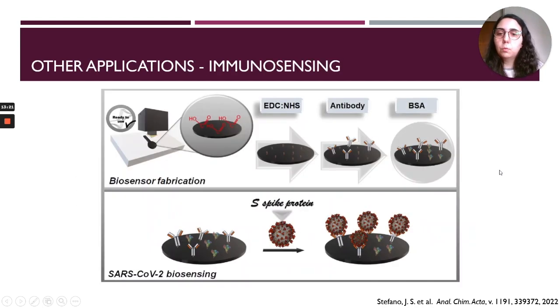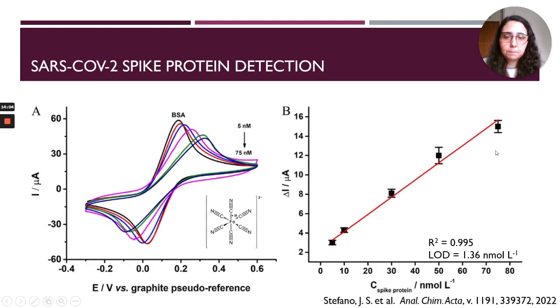We also wanted to do some immunosensing with this filament, and doing some FTIR experiments, we found out that we do have some carboxylic acid groups in the surface of the sensor. So we can use EDC and NHS coupling to add antibodies and couple them covalently to the surface, and we used some BSA to block the remaining surface groups that were still active after antibody immobilization. We used this immunosensor to detect spike protein from SARS-CoV-2 as, again, a model analyte.